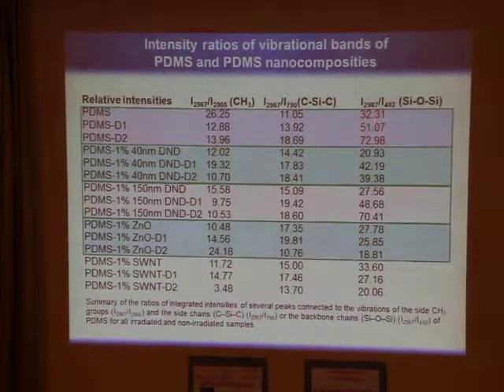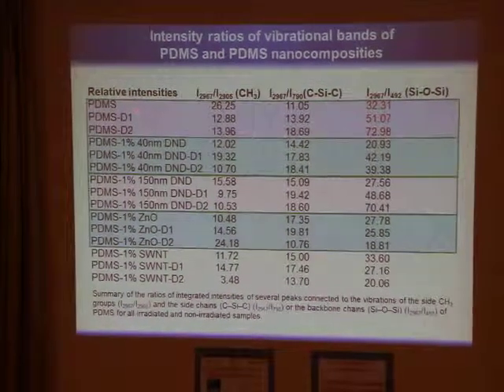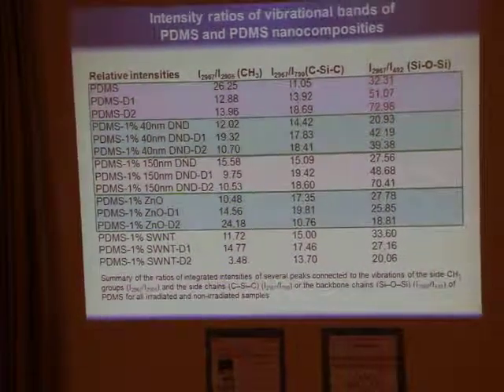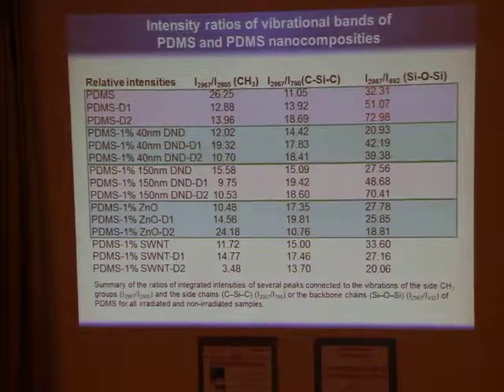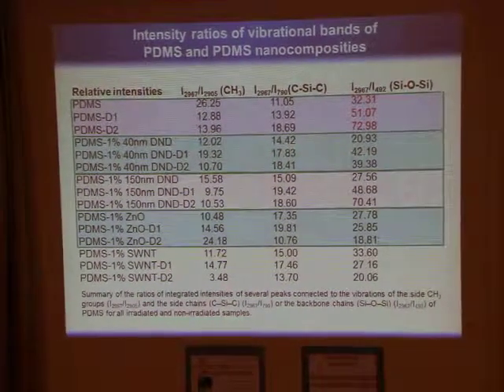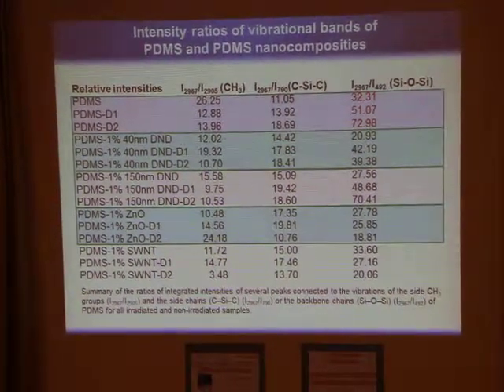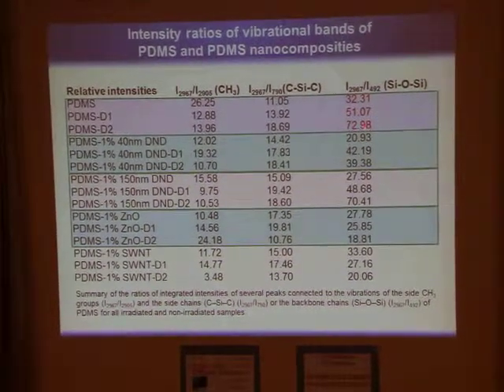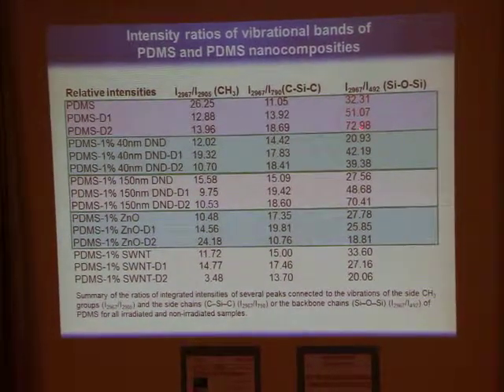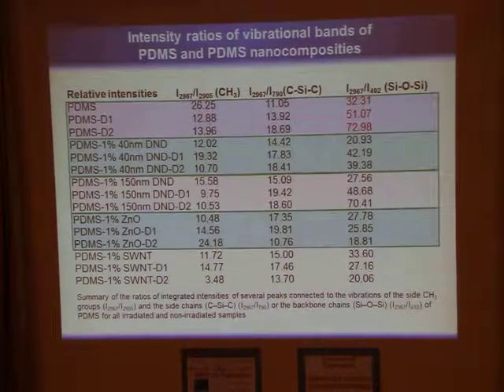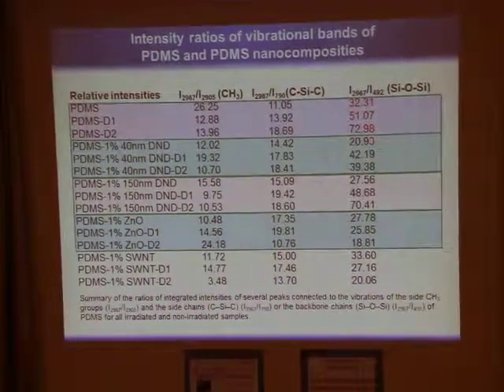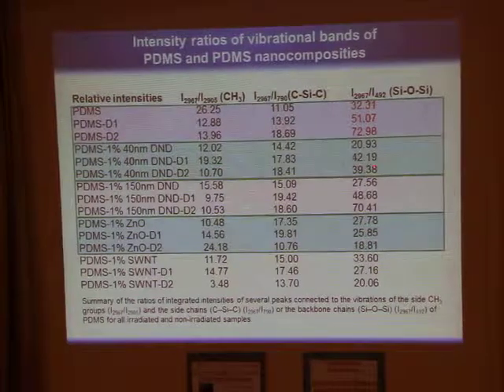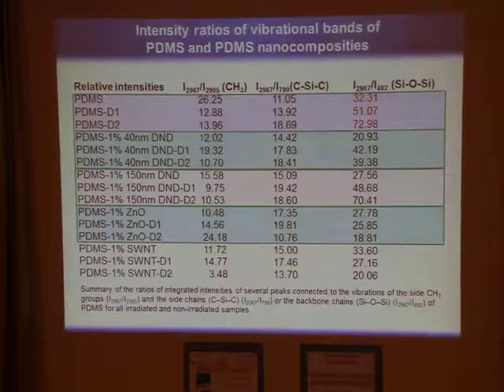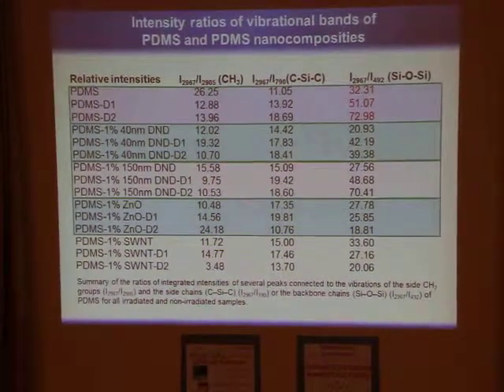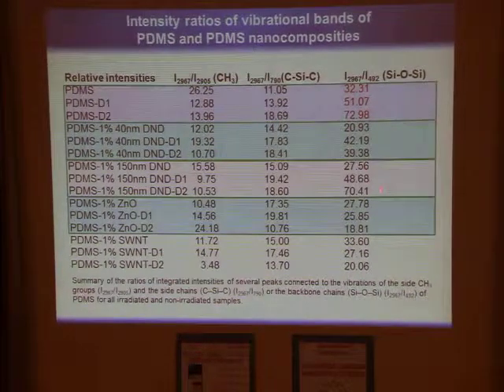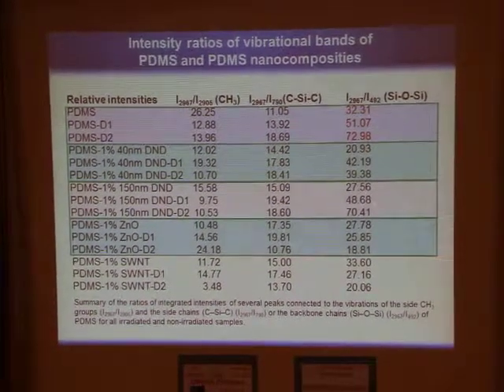So with increase of the irradiation dose, the Si-O-Si bond becomes kind of destroyed, and the increase of this ratio tells us about this fact. What we can see is that with 40 nanometer diamonds, this ratio is not as high, while for 150 nanometer nanodiamonds, it's similar to pure PDMS.